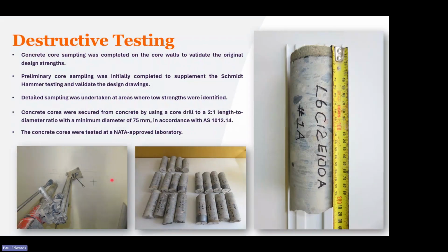And therefore, having identified relatively quickly an overview of what the concrete compressive strength in the building was, by having that Schmidt hammer testing data, it was possible to then focus destructive testing. So representative concrete core samples were taken throughout the building, and I'll go into some further detail about where further concrete cores were taken following non-destructive tests to indicate areas of potential weakness. These cores were taken both to calibrate and then to further identify low strength areas.